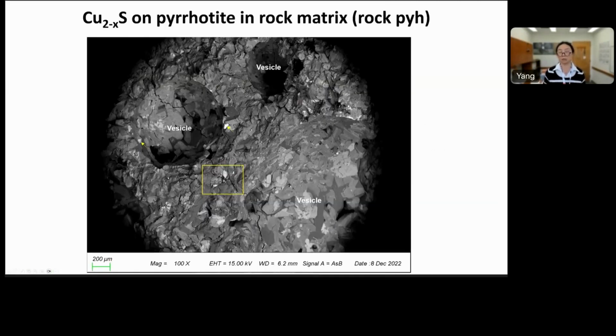In addition to seeing the copper sulfide on the iron sulfide on vesicle walls, we also found copper sulfide on the fractured surface of iron pyrrhotite inside of the rock. So here is an overview of the chip we observed. There are abundant vesicles. There are two sulfide grains over here, one clearly on the vesicle wall, one slightly recessed. And we are going to look at this area, which is between two vesicles.